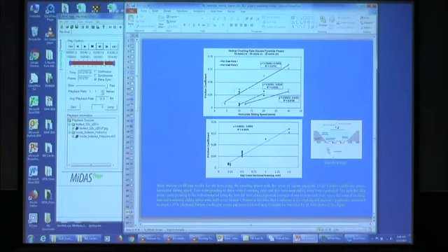We had to do some experiments where we were crushing ice against rough surfaces. Rough on the scale that you see here means prominences on the surface sticking up by a millimeter or so. We were crushing ice against that surface, but also sliding the ice at the same time. And so we had friction data that looked like this.